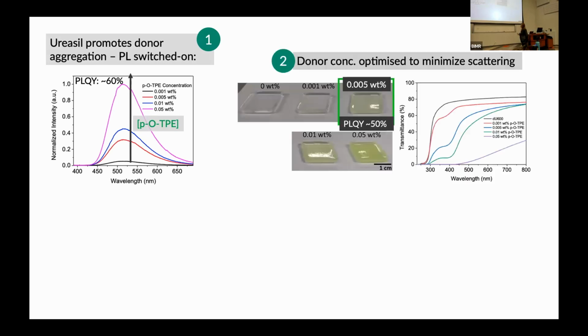The problem is, if you're aggregating a polymer within your host material, you're forming aggregates of the size that scatter light. And you can see that then in the samples. So they start off when we've got no polymer in there, they're really transparent. But as we start to get aggregation, they become cloudier and cloudier. And you can see that in the transmittance spectrum. They're really, at this point, unacceptable. So we have this trade-off because we want the luminescence and the aggregation, but we don't want the cloudiness and the light scattering.